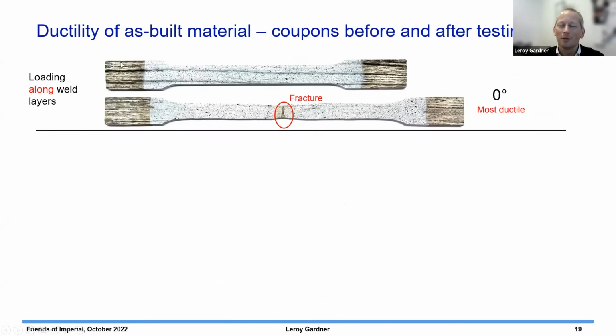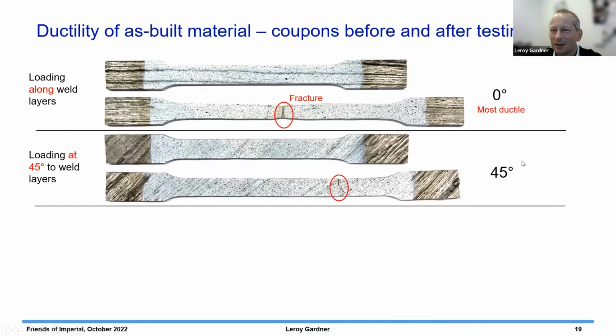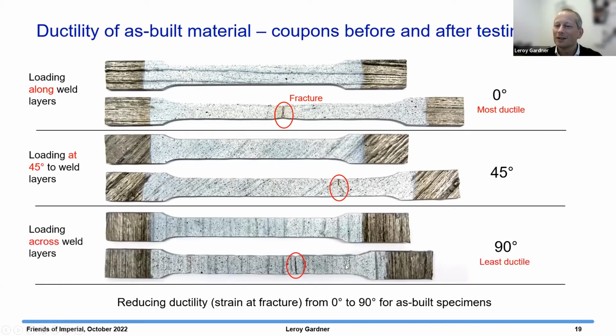So here's a coupon where we're pulling along the line of the weld layers. The top one is before testing. The second one is after it's fractured in the middle. And you can see there's a good amount of elongation here before failure. So that's a ductile response. 45 degrees, it's a bit less ductile. And then 90 degrees, it's quite a lot less ductile.